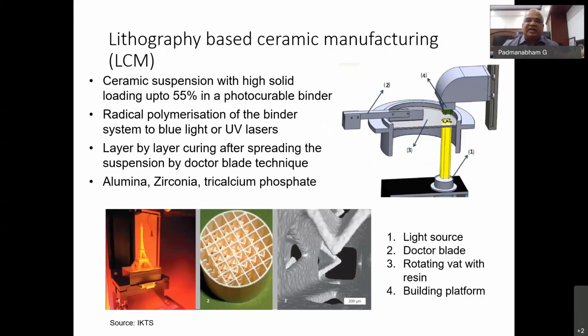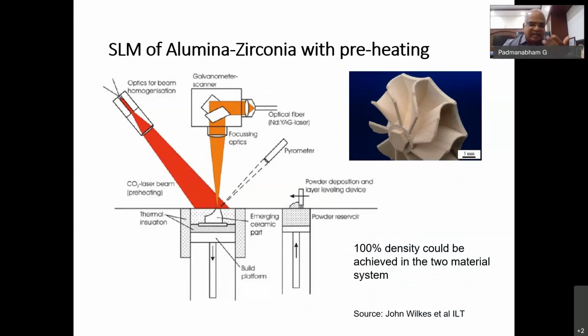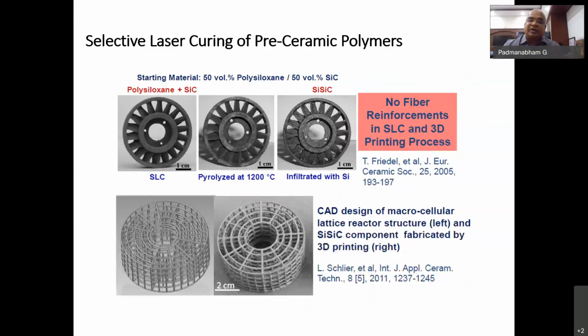And then various techniques are available now, such as lithography-based ceramic manufacturing. Basically, you have a ceramic suspension in a photopolymerizable binder, and with a UV laser, you do the shaping. Similarly, we have SLM itself with a preheating so that melting can actually be done. Then we have the selective laser curing method, where we start with a binder and silicon carbide particles put together, pyrolyzed after 3D printing. And then the porosity that you end up with is infiltrated with silicon, and then you get a good part.